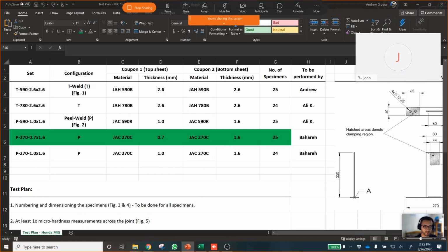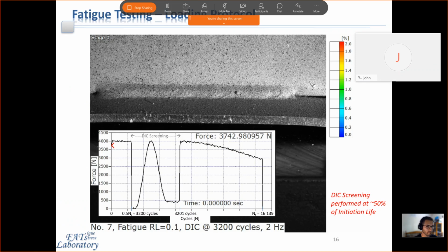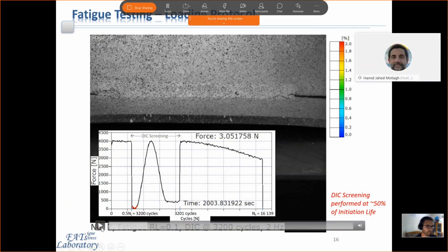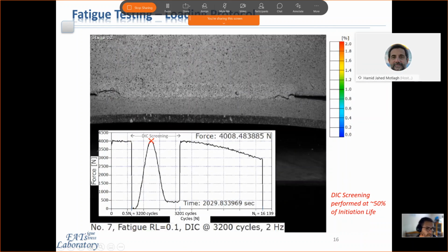Yeah, I mean, you would like to have more measurements for different samples because we are assuming that they would be under the same condition and therefore would have the same state of residual stress. But of course, you would never get the same state of residual stress because of the local conditions in each of these.